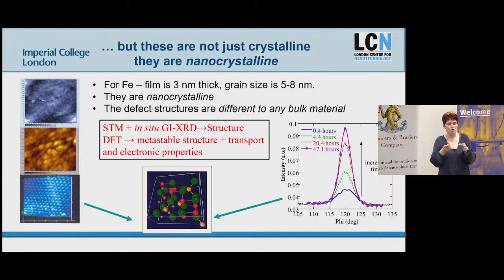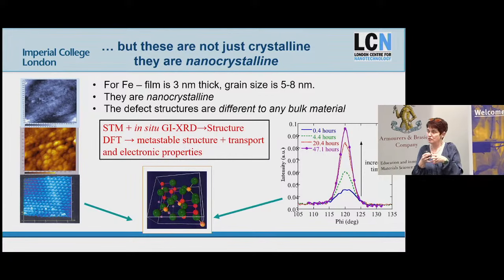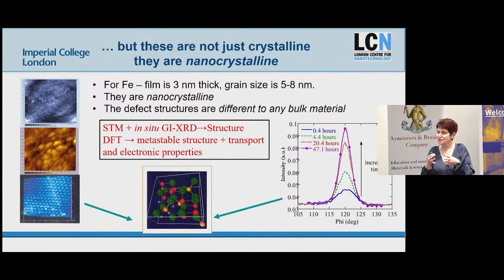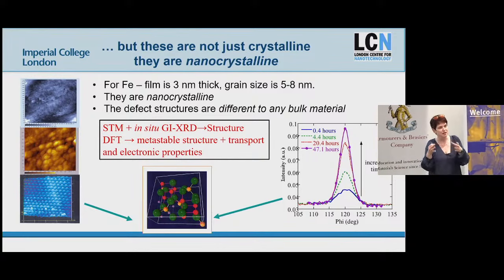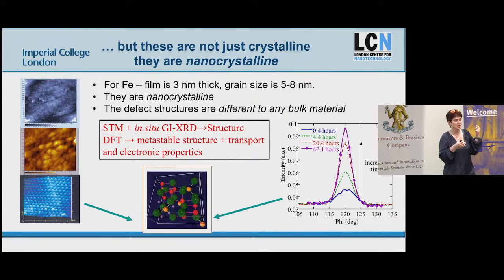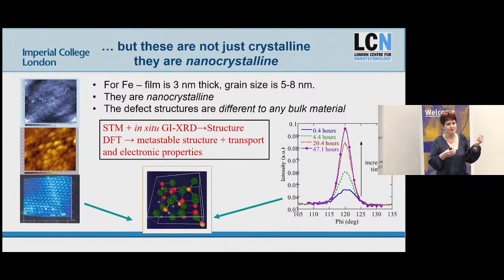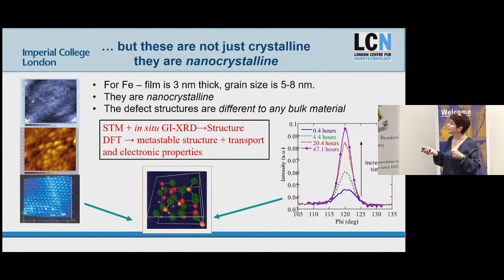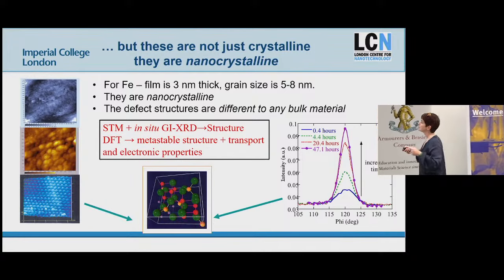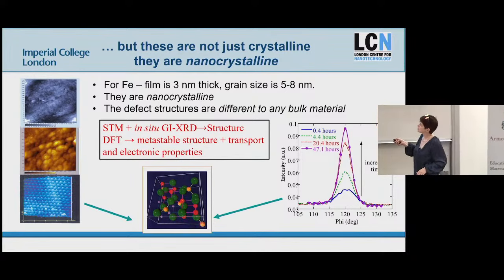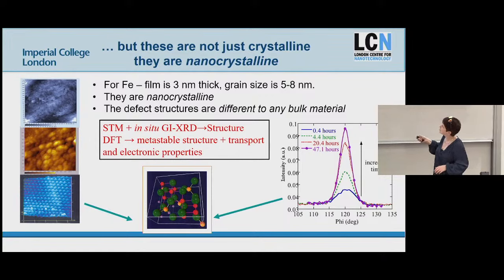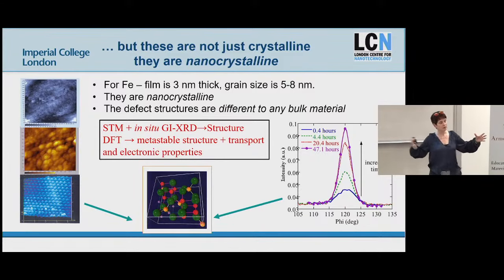It means that we have these little ordered bunches of atoms in grains, but they're ordered on a length scale of 5 to 8 nanometers. Right? 5 to 8 nanometers. So a human hair is something like 50 microns. Right? So we're orders of magnitude smaller in these crystalline domains than a human hair. And so this STM, this is the one I just showed you. So these are atoms all lined up, nicely crystalline. But actually, they're arranged in these little blobs that are about 5 nanometers. If you look at this bigger picture, you can see the outline here of the metal grain that's underneath. That's much bigger.